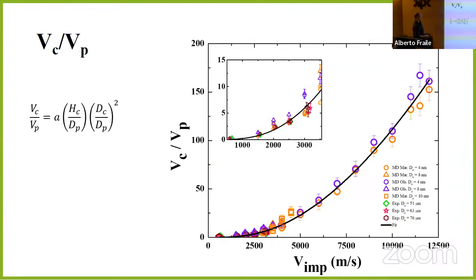But if we divide the volume by the volume of the impactor or the projectile, so we can put this without dimensions, we have all the experiments and the simulations in the same curve and in the same graph. And it can be fitted with this model. I forgot to put a reference, but it's one of the theoretical models for this kind of craters. So the volume looks fine compared to the experiment. The experiment is tungsten on tungsten also. So we are not comparing to a random experiment of some other material. So it's the real one.